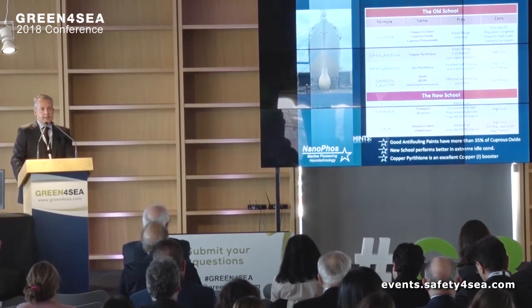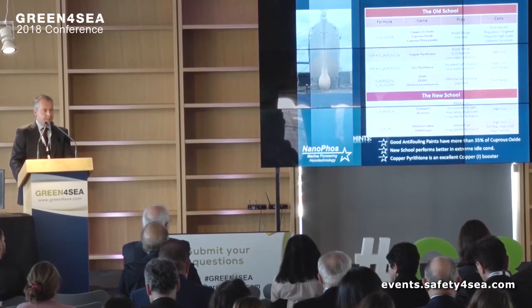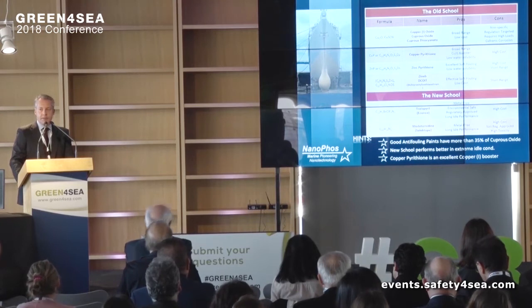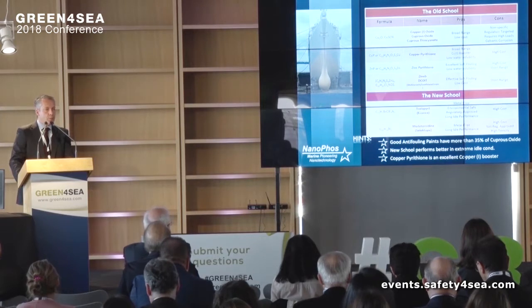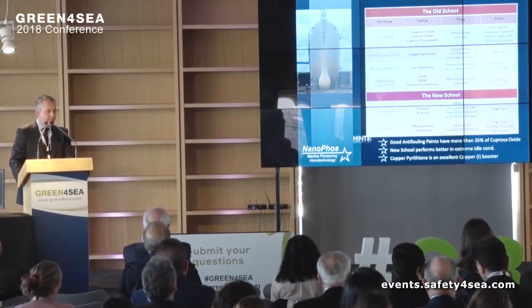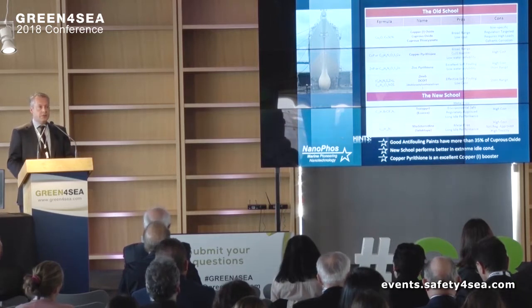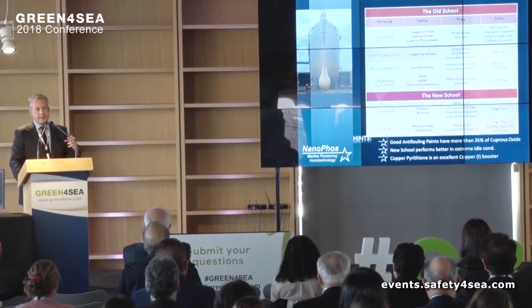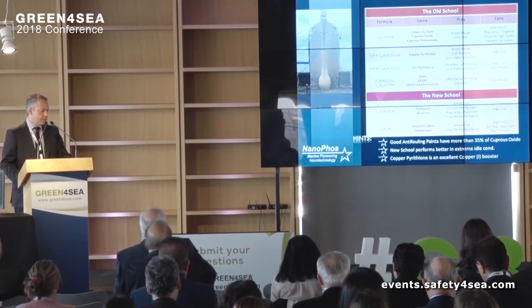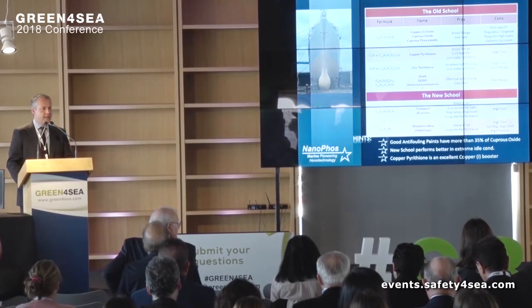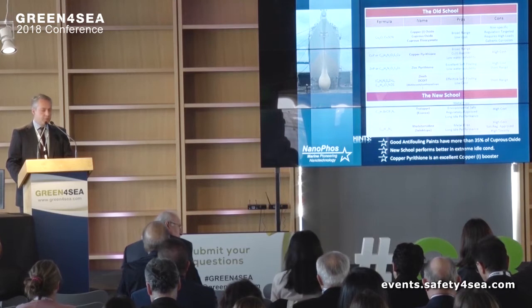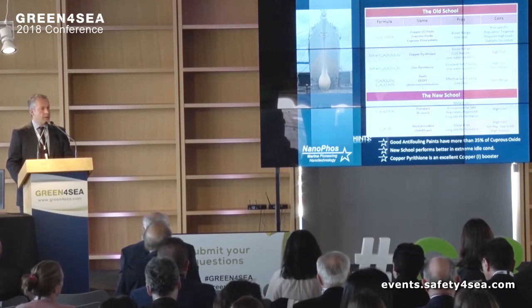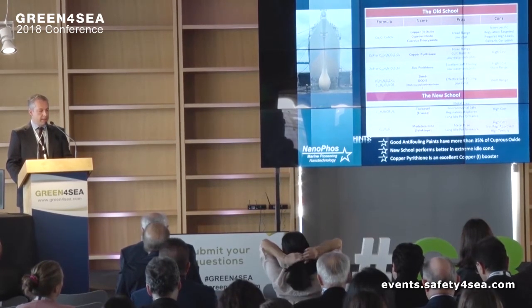All antifouling, especially the self-polishing antifouling systems, contain biocides. After the ban of tin compounds in the early 2000s, the major biocide component of antifouling paint is copper, actually cuprous oxide, copper 1. Copper has a broad range and a low cost, but it has to be overloaded inside the paint in order to give good results. Actually, there are some organic antibacterial or antifouling biocidal components, and there is a new trend of very, very specific molecules that have been developed especially by pharmaceutical companies in order to provide antifouling properties in long idle conditions.